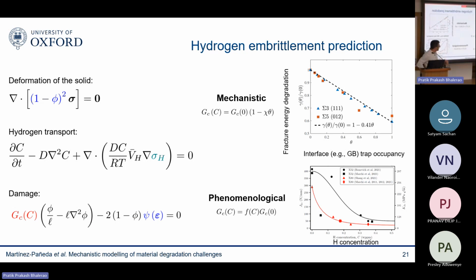But the two approaches that we have pursued are, on the top, the more mechanistic approach. We try to understand the physics of this problem. We try to come up with a degradation law that does not rely on extensive experimental calibration. And to do that, we basically solve the coupled problem. This allows us to predict how much hydrogen we have at a critical interface. Let's say that you're interested in a grain boundary. So by solving this deformation problem, I know how much hydrogen I have on my grain boundary.